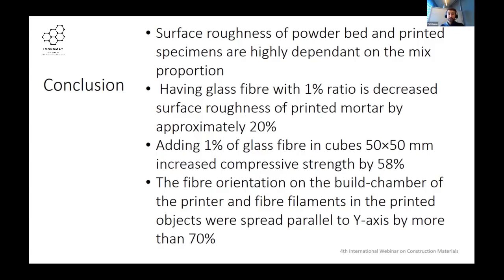If we are printing this, the surface roughness of the printed mortar with 1% glass fiber has about a 20% improvement. Also, adding 1% glass fiber improves compressive strength pretty well, by 58%, or we can say around 60%. And regarding fiber orientation, using ImageJ analysis, we found that most of the fibers are parallel to the y-axis in the powder bed of the inkjet 3D printing technique. So this can be figured out by doing an ImageJ analysis.